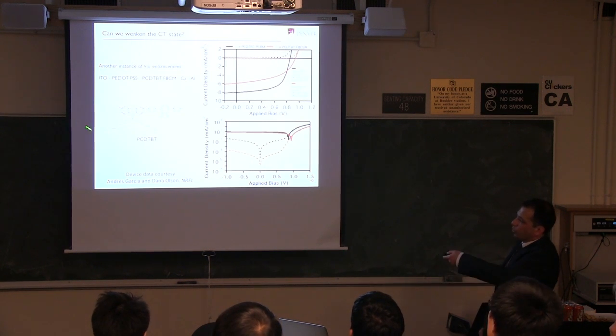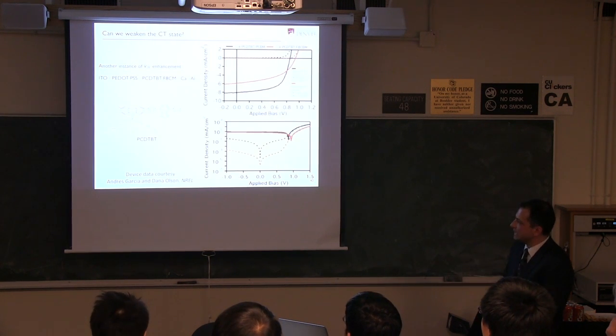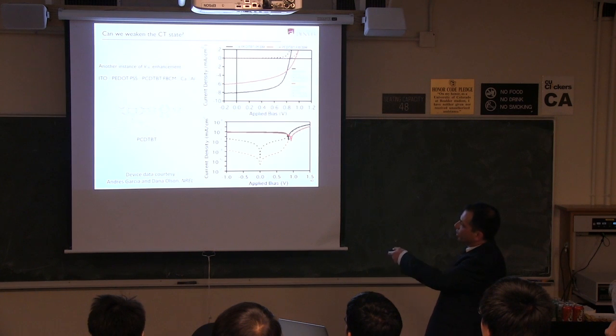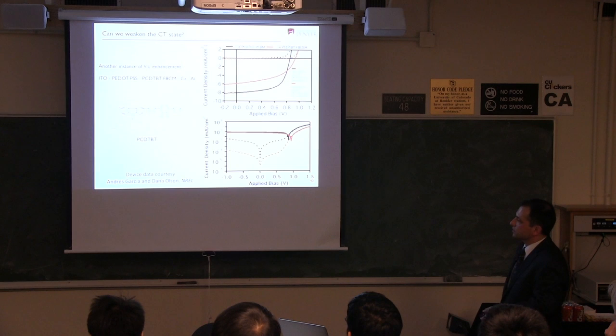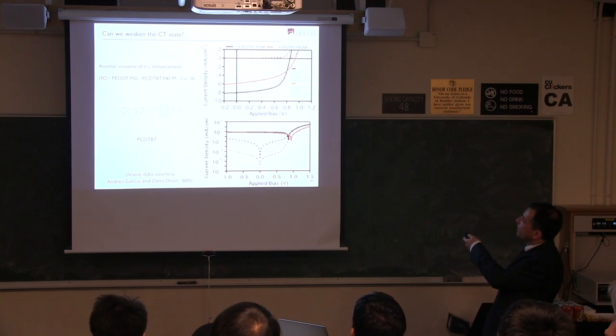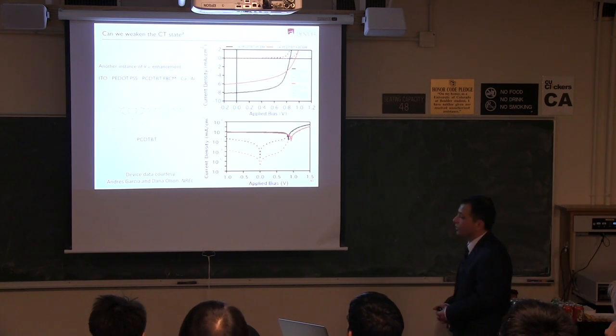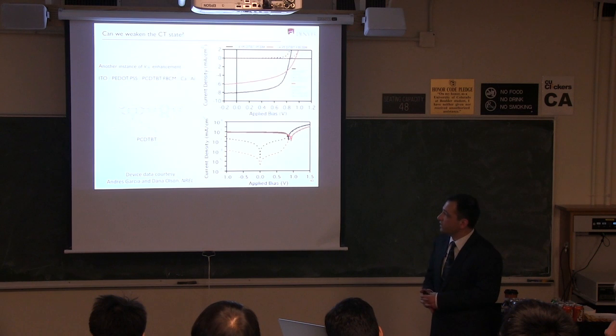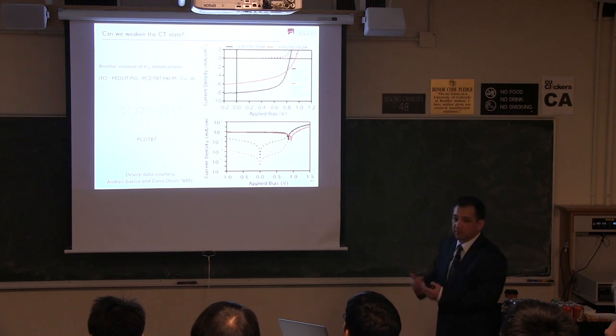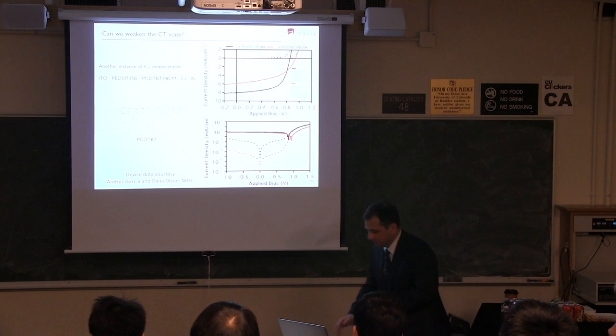So here is another workhorse polymer we have, PCDTBT. This is a polycarbazole unit with a benzothiadiazole. That's what the BT is about. This is a lower band gap material that we like to use. And in this case, we jump up about 80 millivolts of voltage when we put in this new acceptor. So we think we can tune the strength of that CT state a little bit. Obviously, we haven't improved the efficiency yet with this technique, but the distance between the donor and acceptor is something to consider. It has to be an optimal value.